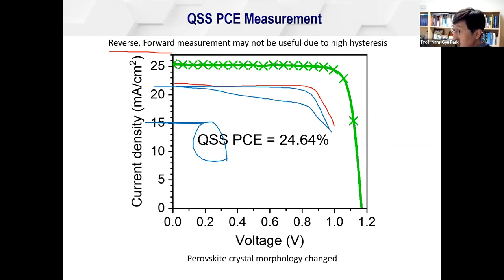So far, 30 to 40% MACl is very important. And our group uses some amount of cesium chloride. It works better than only MACl. For FAPbI3 perovskite, to achieve long-term stability, usually with methyl ammonium chloride, if you use a small amount in the precursor solution, you cannot have high efficiency. But if you have a large amount, usually the high efficiency solar cells, for instance, Professor Sang-il Seok's group and other Korean groups, they always use more than 35% methyl ammonium chloride.